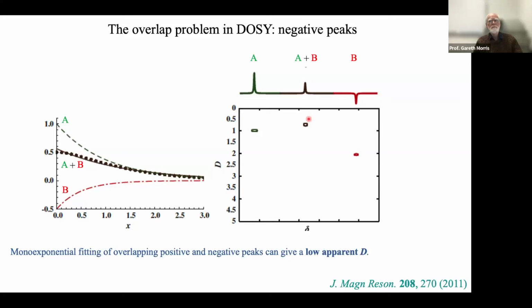So if we have negative signals, we can get really confusing results. Now, how could we get a negative signal from an experiment that starts with a positive spectrum? The reason is that we're normally doing experiments in proton NMR, and protons tend to be coupled to each other. In order to get diffusion weighting, we have to have transverse magnetization to hit with gradient pulses. And whenever we have transverse magnetization, individual multiplet components are dephasing.